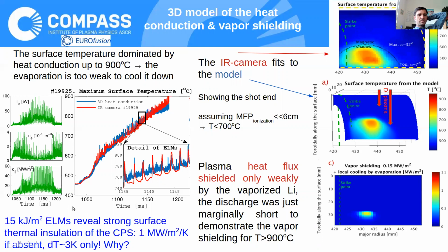And in order to resolve them in the model, we had to assume pretty strong surface thermal insulation of the capillary pore structure, about 1 megawatt per square meter per Kelvin. If we didn't do this, the temperature would rise only by 3 Kelvin. We don't know really why. The calculated vapor shielding in this case was only 0.15 megawatt per square meter, because it's spread over an area 100 times larger than the hotspot itself. And at the hotspot, it was cooled by the latent heat of vapor, which was up to 1 megawatt per square meter, not larger than this.